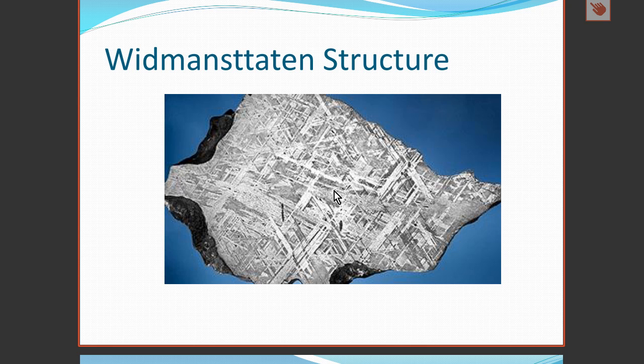In this iron nickel meteorite, it is estimated that in order to produce a Widmanstätten structure that is this coarse and so visible to the naked eye, it would have had to cool at a rate of less than a degree drop in temperature over 1,000,000 years. So it is then suggested that these must have formed at the center of an object such as a planet.